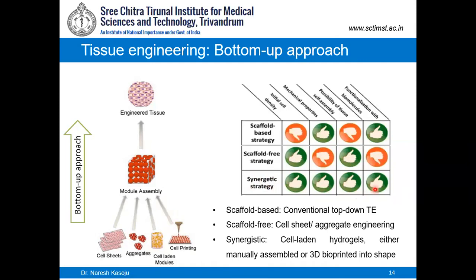Whereas the synergistic strategy, which is hydrogel based systems or 3D bioprinting systems, has all the advantages. You can exactly control the cell density. If I take 100 cells in a hydrogel system, I am very sure that all the 100 cells are there in the gel. There is no loss. I can fine tune the stiffness of the gel in order to fine tune the mechanical property. I can also self-assemble those hydrogels in a layer by layer fashion or other modes of assembling. I can also introduce biomolecules into the hydrogel in order to make it a functionalized system. That is why 3D printing, or this sort of additive manufacturing technology, has really taken the front seat in this particular field.